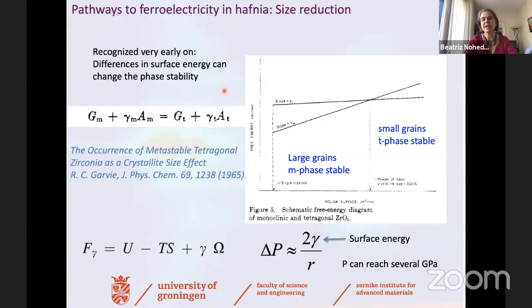Hafnia and bulk zirconia are not ferroelectric. They have been known for many years, and no sign of ferroelectricity has been seen in them. And this was one of the mysteries of the material. Why is hafnia suddenly becoming ferroelectric at the nanoscale? And the answer to that is actually in the surface energy. So it is possible by reducing the size of the material to increase the surface energy contribution such that the phase stability changes.